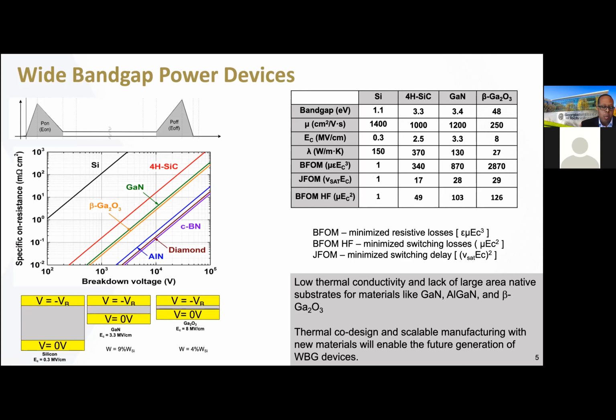However, when we look at where we are today, going from silicon to silicon carbide to gallium nitride to beta gallium oxide to aluminum gallium nitride, we're seeing a lack of large area native substrates to grow on. That's going to give us issues in terms of how we grow once we move past silicon carbide. Also, as we start getting into ternaries like AlGaN and into beta gallium oxide, the thermal conductivity starts to drop, and it drops very far. So now we're going to have issues in terms of thermal. Even though we have these nice figures of merit, we have some issues to deal with in terms of the engineering and device integration into packages.